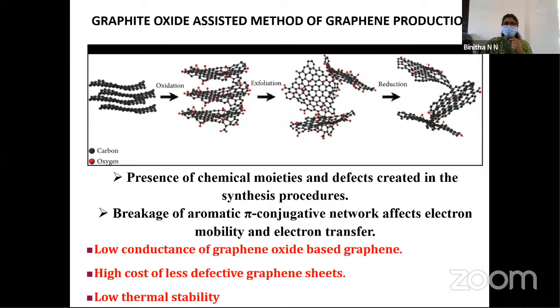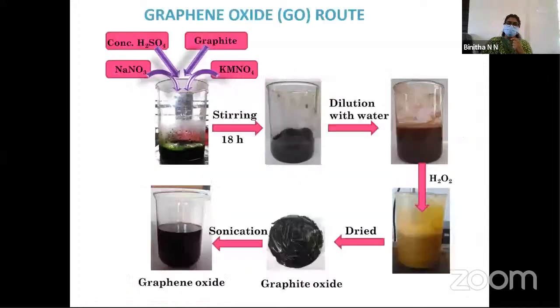Another issue of graphene oxide derived graphene, or reduced graphene oxide, is its low thermal stability. It starts to decompose from 150 degrees Celsius onwards. So we cannot apply it for high temperature applications. These are photographs of different stages of graphene oxide preparation. Oxidizing agents such as concentrated sulfuric acid, KMnO4, etc. are used. Lots of fumes are evolving there. In some stages, the temperature should be kept below 50 degrees Celsius. And as a whole, the process is highly tedious, time consuming, and hazardous.